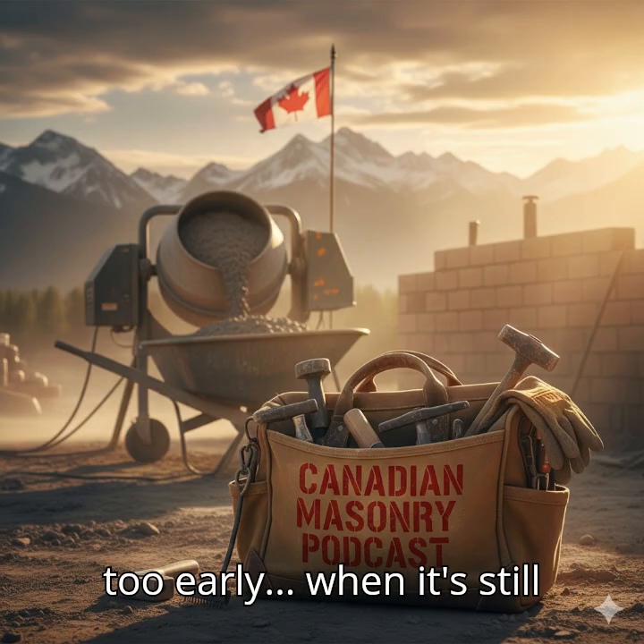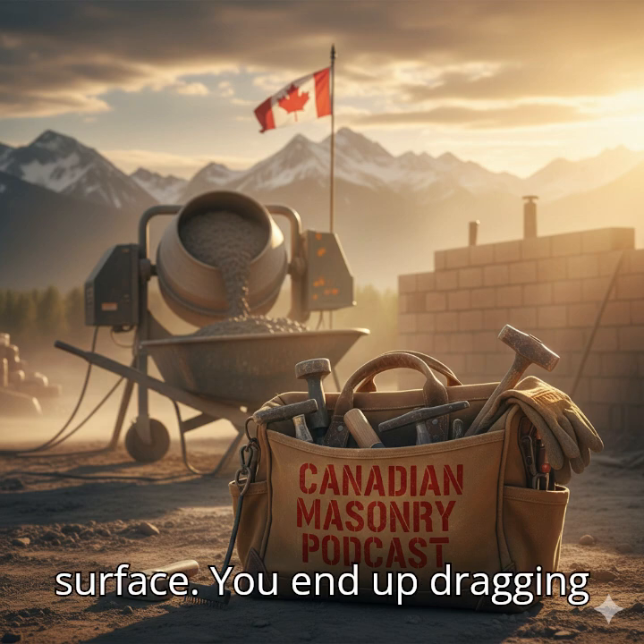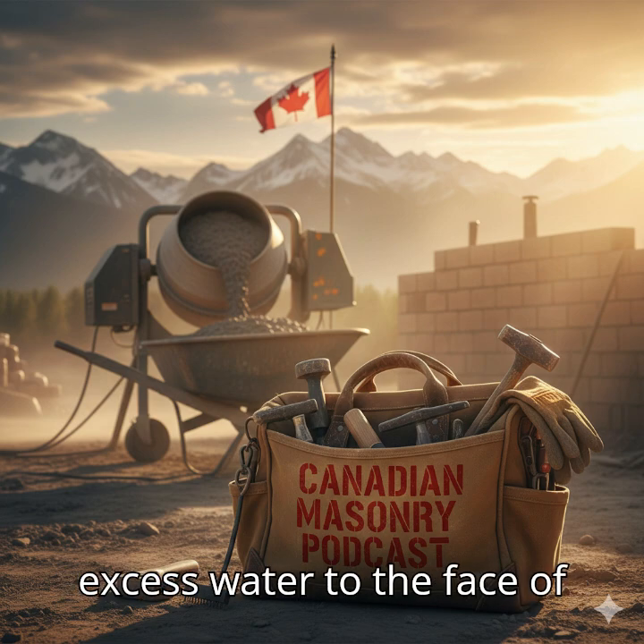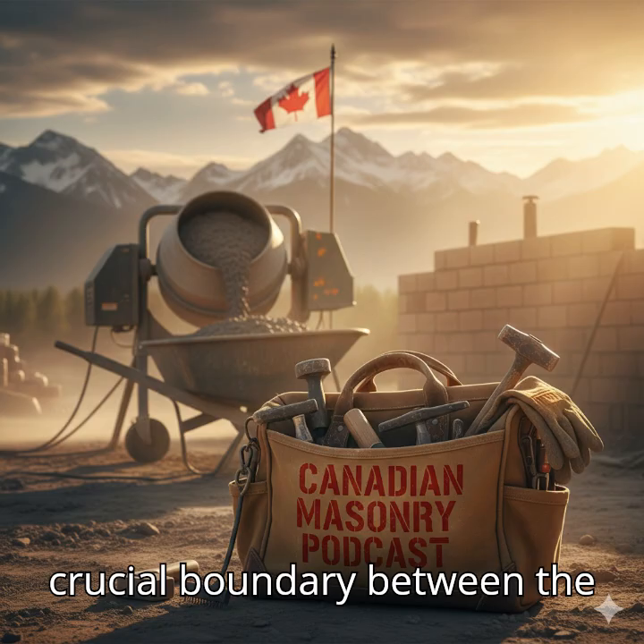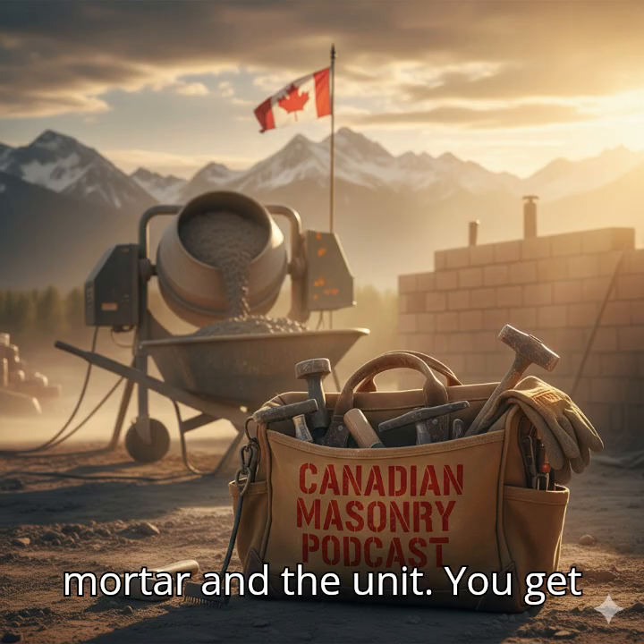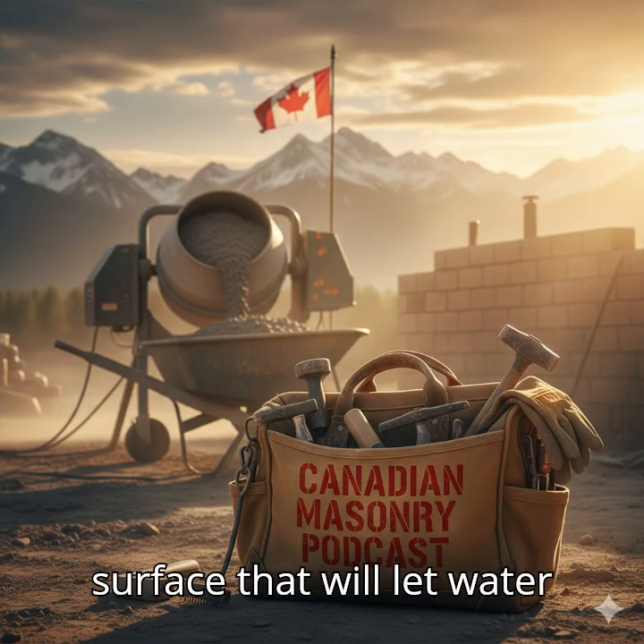And if you tool it too early, when it's still wet, you'll just smear the surface. Yeah. You end up dragging excess water to the face of the joint, which weakens that crucial boundary between the mortar and the unit. You get a poor, low-density, brittle surface that will let water in.